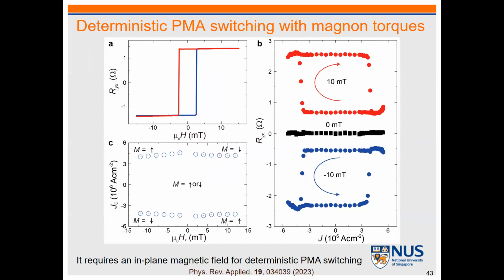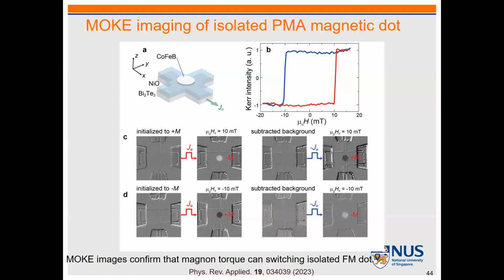But once we apply a very small in-plane field along the current direction, then we can switch. The opposite magnetic field will give the opposite switching polarity. So the operation of this PMA switching using magnon torque follows exactly the same as the conventional spin-orbit torque system. And to prove this, we can also switch an isolated magnet.